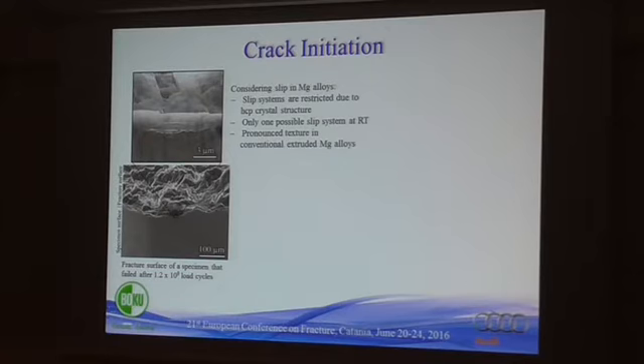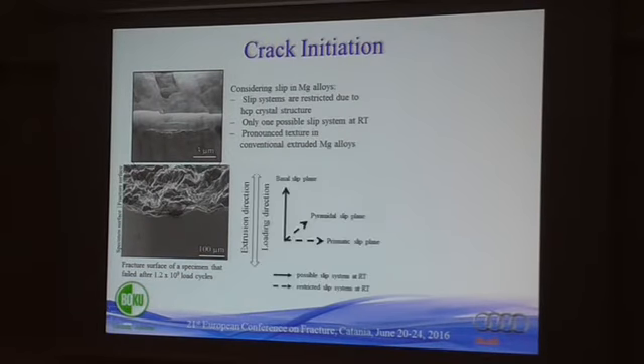And considering slip in magnesium alloys, one has to take into account that slip systems are highly restricted due to the hexagonal close-packed crystal structure. And even more due to very high critical resolved shear stresses, there's only one possible slip system left at room temperature. And it has been often shown by many authors that these conventional extruded magnesium alloys like the AZ61 are given a pronounced texture during the process, which results in the only possible slip system, the basal slip system, coming to lie parallel to the extrusion direction, which in our case is also parallel to the loading direction, which makes this slip system very unlikely to be activated.